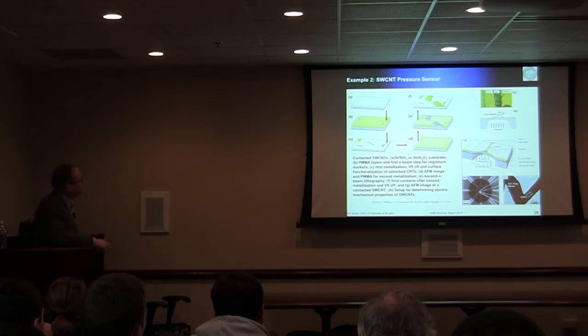Probably this one was the smallest pressure sensor we've ever made. This one is a very small diameter device. The diameter of this is on the order of 100 microns. This device was done in collaboration with the ETH Zurich group, Christofer Hierold's group. And what we did here, we used ALD to make a membrane, and we used single wall carbon nanotube as a piezoresistive sensor on top of the membrane. So as the membrane deflects, it pulls on the nanotube and its piezoresistive properties change.